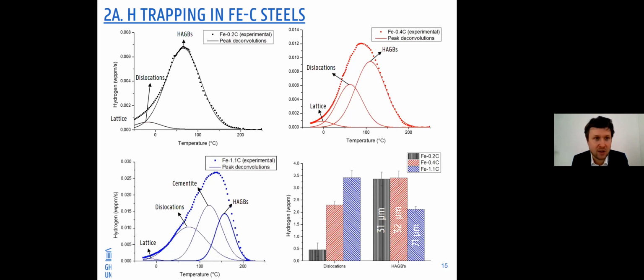What is also needed to take into account is that the amount of hydrogen, so the area under the peak, should be the same independent of the applied heating rate. So these are restrictions and things you have to take into account when you do such deconvolution. If you do this with a lot of care and by coupling it with the microstructure, you can be sure about the trapping site. It's not because you obtain an activation energy of 30 kilojoules per mole that you can say this is dislocations because literature tells me so. You need to know your materials, you need to change the microstructure, and then only you're sure about what you see and how you can deconvolute such a spectrum.